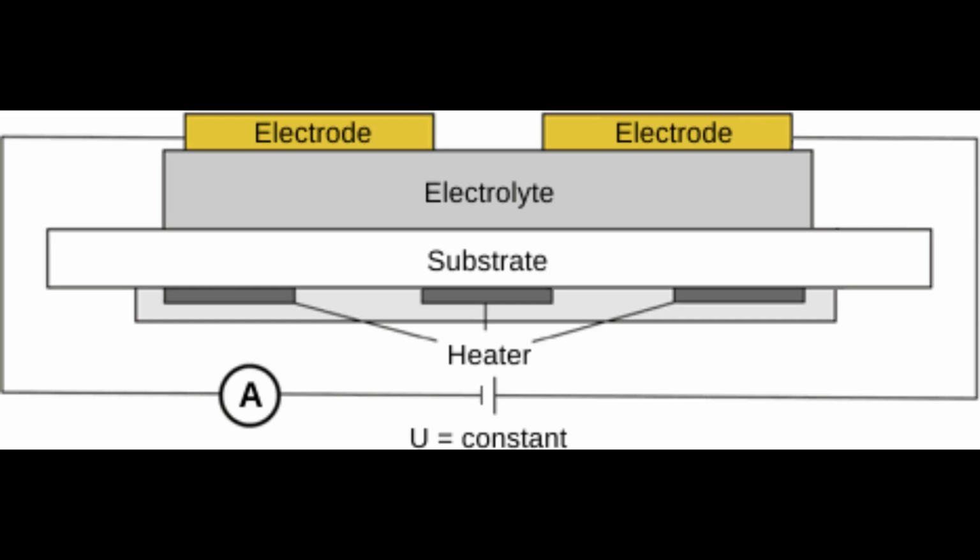Due to the high temperature of the combustion environment, only certain types of materials can operate. The majority of NOx sensors developed have been made out of ceramic type metal oxides, the most common being yttrium stabilized zirconia, which is currently used in the decades old oxygen sensors. The YSZ is compacted into a dense ceramic and conducts oxygen ions at the high temperatures of a tailpipe, such as 400 degrees centigrade and above.